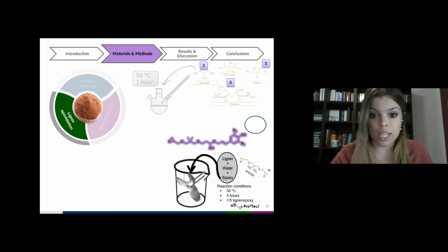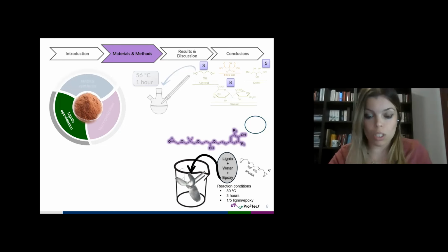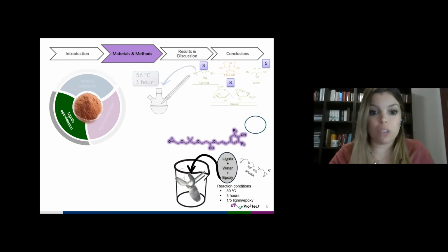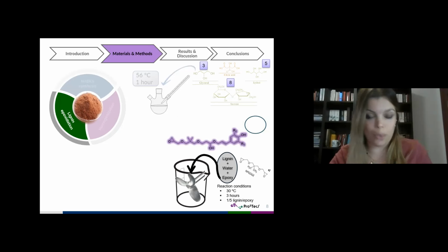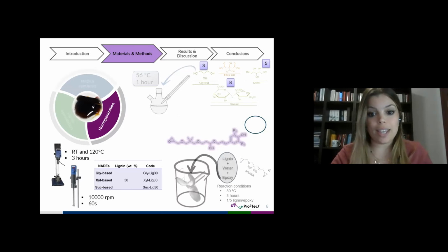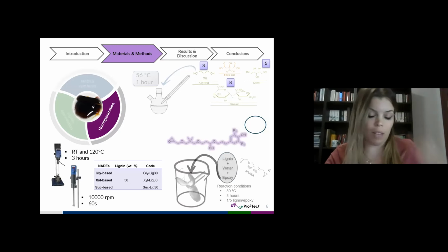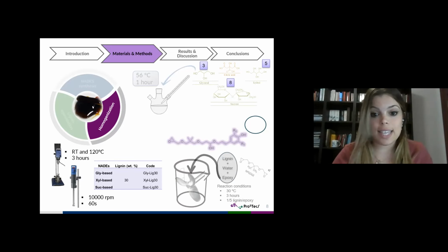carrying out the reaction with neopentyl glycol diglycidyl ether and mixing lignin, the epoxy compound, and water in an open vessel at room temperature for 3 hours. Finally, the product was centrifuged, washed, and dried just to obtain the epoxidized material. And in the last step,